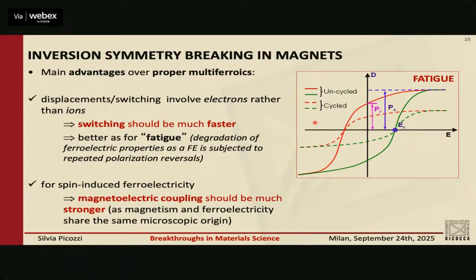Second thing is that the magnetoelectric coupling is much stronger if you have ferroelectricity driven by spin degrees of freedom, right? Because ferroelectricity and magnetism share the same microscopic origin. You cannot have ferroelectricity without magnetism, and vice versa. So once magnetism develops, ferroelectricity is bound to it. So the coupling and the origin is exactly the same one. So they're tightly connected.